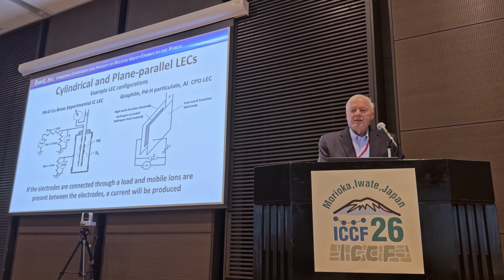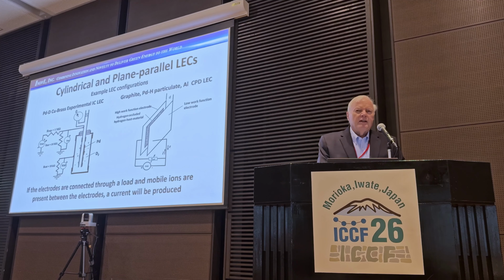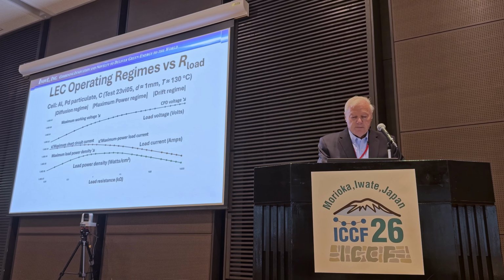When we started doing calculation of coefficient of performance a few years ago, we realized that when we reduced the voltage we were applying, the coefficient of performance went up. So we reduced the voltage a little more, the coefficient of performance went up. You eventually get to the point where you say, well, hell, let's just turn off the current supply. We did, and we got more, but we still continue to get voltage and current. So that was the realization that, by God, this may be real. On the right, you see just a different form fit, planar selection, and in some ways it's a little easier to construct and also to maintain the separation distance.